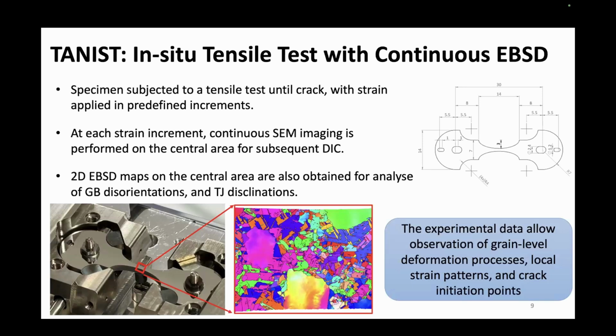So to check our hypothesis, we conducted an in-situ tensile test with continuous EBSD monitoring, which is called the TANIST. In this test, a specimen is subjected to a tensile test until it cracks, with the strain applied in predefined increments. This is the specimen geometry and how it is assembled in the machine. With this machine, we can take an image at each predefined strain level, so we can observe the surface change in real time under load. At each increment, we get continuous SEM images, which let us observe the material deformation and allow for